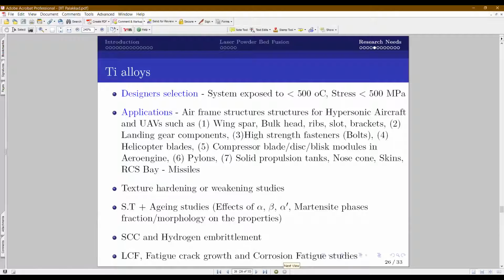Looking at the designer's perspective, titanium alloys are chosen wherever the temperature doesn't exceed 500 and stress level is less than 500 MPa. Similar applications as aluminium are in hypersonic aircraft and most of the engine compressor regions, pylons, and some of the missile parts where titanium is very much used. Titanium by nature forms a texture during any forming process, and as we all know, forming certain kinds of texture can give either a texture hardening effect or a weakening effect. This process, by virtue of its nature, also forms texture and grain orientations. So understanding texture development in 3D printed titanium alloys is of paramount importance.